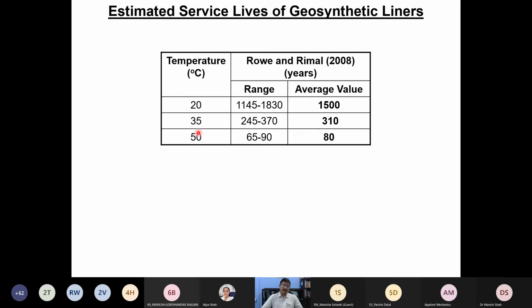And the same geomembrane subject to 35 degrees, then the service life dropped down to 310 years. When the geomembrane is subject to 50 degrees, which is quite possible in the case of North American landfills, then your service life goes down to 80 years.